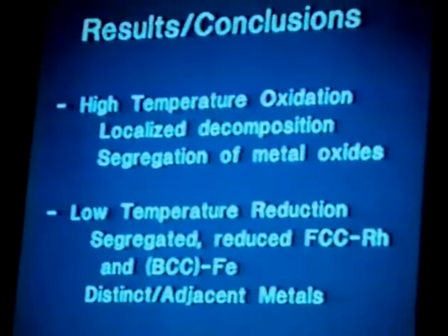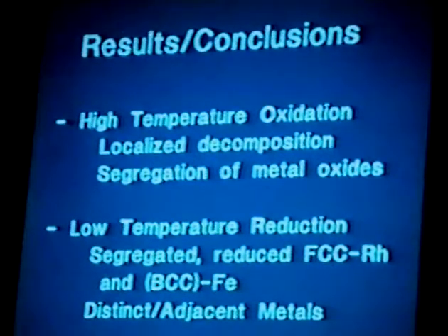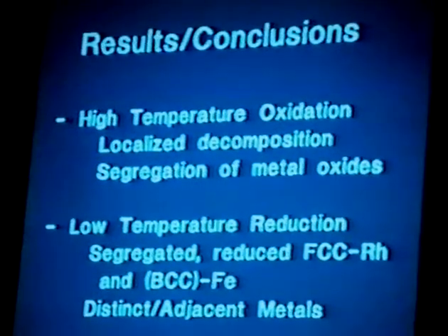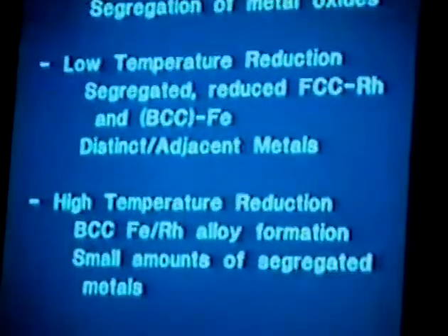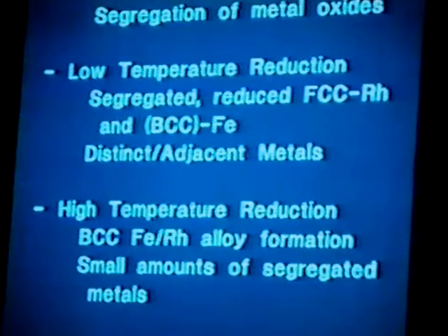Now, on the basis of the X-ray and the Mossbauer work, what we concluded, without getting into the details of the data, was that when we oxidize these supported metal particles at high temperature, about 200 degrees C, what we ended up with was a localized decomposition of the iron and the rhodium into separate zones of iron oxide and rhodium oxide. They existed essentially as microcrystals inside larger, what I'll call bimetallic oxide agglomerates. They were larger particles consisting of microcrystals of separate iron oxide and rhodium oxide.